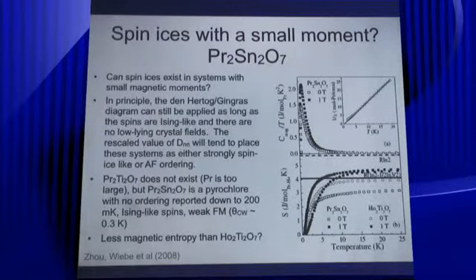But this is some data from praseodymium stannate that we prepared. It has a characteristic anomaly at low temperatures, and you recover some of the entropy when you apply a field. If you measure Curie-Weiss susceptibility, it has a weakly ferromagnetic Curie-Weiss temperature, and there's no ordering reported down to 0.35 Kelvin. This is looking at the heat capacity of the stannate compared to holmium titanate. And if you look at the holmium titanate, you get the spin ice entropy integrated back. The praseodymium stannate has roughly 75%, so there's some missing entropy at low temperatures. And again, if you apply a field, they look similar. They recover basically the same entropy among the two different compounds.